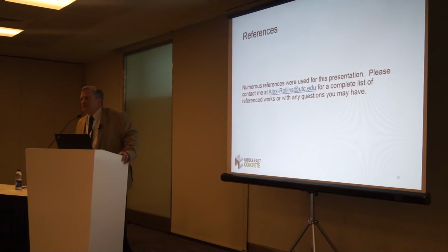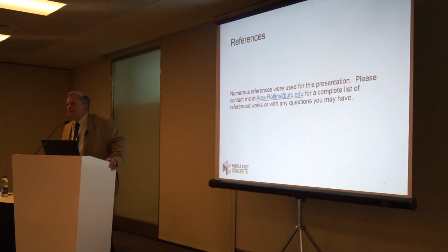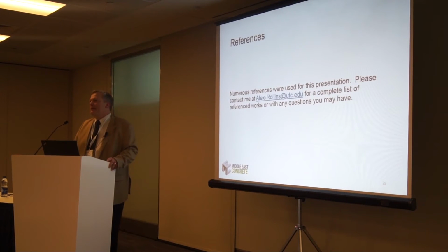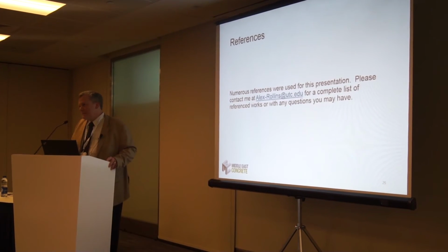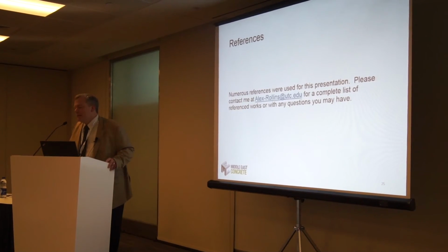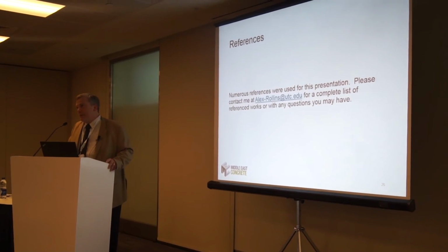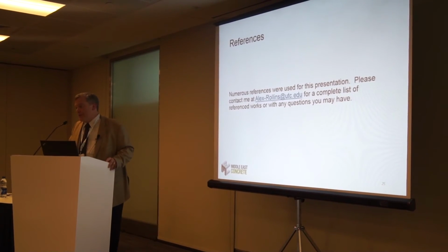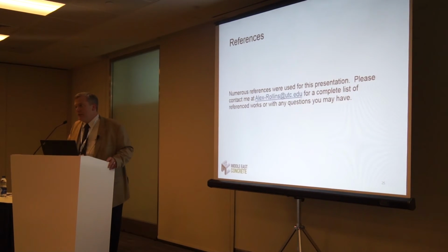Talking about fair face concrete and architectural concrete, is it compatible with that? Is it compatible with most common paints also? It is, and I can't explain why, but this particular material leaves the top 1 to 4 or 5 millimeters unreacted for the most part. So adhesives in the case of flooring, paints, colorants, there have been no issues with any of that that I'm aware of, because it somehow leaves that top surface unreacted.